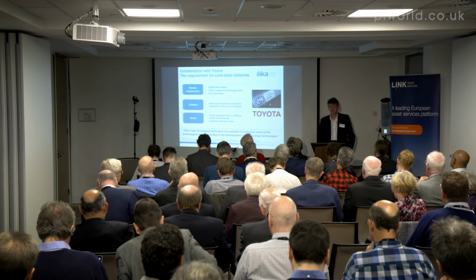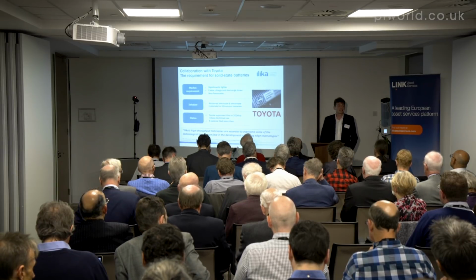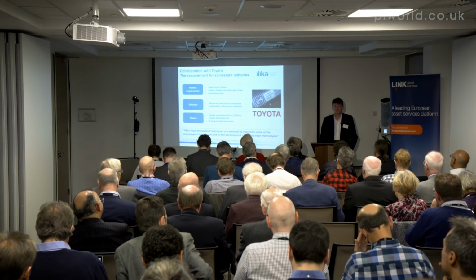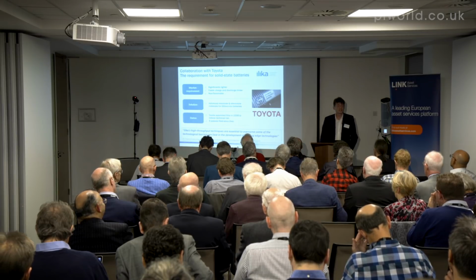So Toyota were interested in trying to make lithium-ion batteries that were intrinsically safe, and they do that by removing the liquid electrolyte and replacing it with a solid electrolyte that you can't set fire to. Sounds straightforward. Actually, it's quite tricky, quite difficult to achieve. You need to come up with a series of ionically conductive materials. We spent about 5 years screening those materials and found a subset that have got the right ionic conductivity but electrical insulating capabilities so that the battery doesn't short.